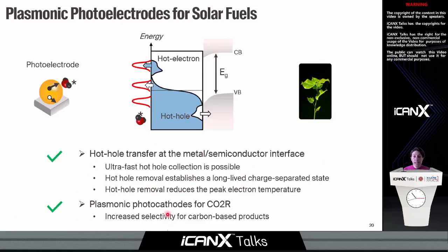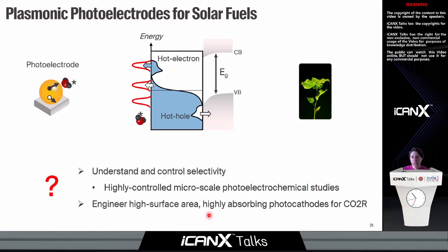So this brings me to summarize these past results. Indeed, we have shown that by testing this plasmonic photocathode for CO2 reduction, we have been able to observe enhanced selectivity for carbon-based products against hydrogen evolution. But still, there are many open questions in this field that need to be addressed. And I think the use of photonics and nanophotonics is going to play an important role, because we have to be able to improve our capability of controlling the properties of these plasmonic nanoparticles during the chemical reaction.